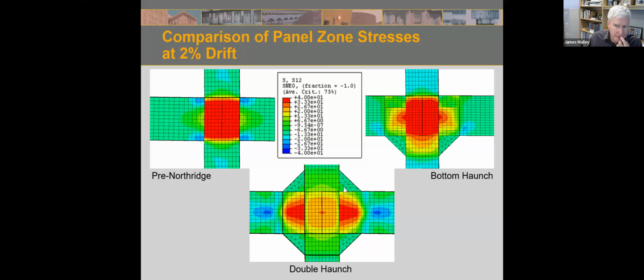And you can see the interesting thing about the single haunch is that on the Pre-Northridge, you can see very kind of high shear strains in the column panel zone. And that's what leads to what we call kinking. And you can see that a little bit here in the flanges, where you don't have a straight line here. It sort of has a kink at the corner of the panel zone here. Very high strains happen there. And that's what causes, when you have weak panel zones, you are going to get a kinking in the flange. And we've seen that fracture in the Pre-Northridge connections before we get much yielding out in the beam.